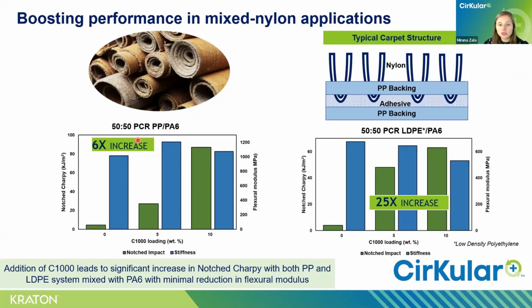Even more impressive is that this boost in impact strength came with a minimal reduction in the flexural modulus, which means that we were able to achieve a better balance between toughness and stiffness, which is critical for high performance applications.